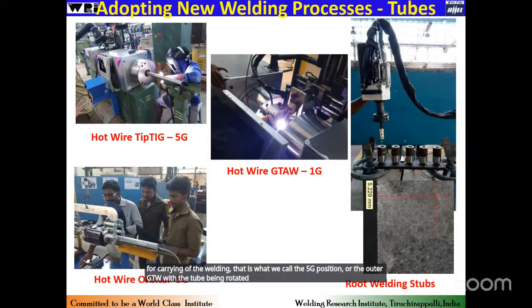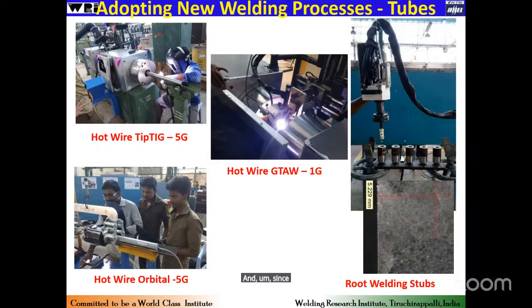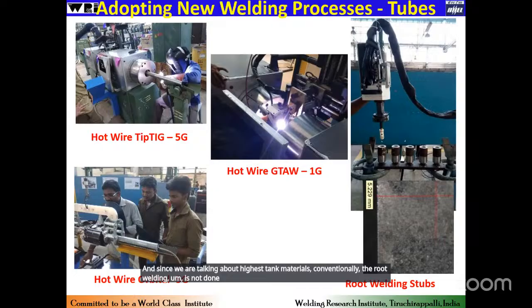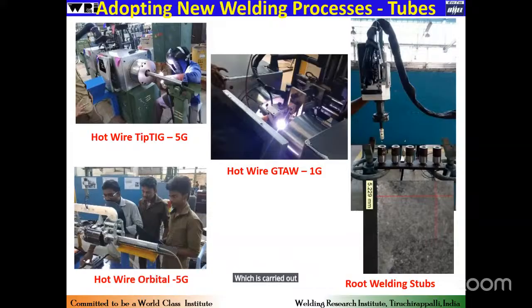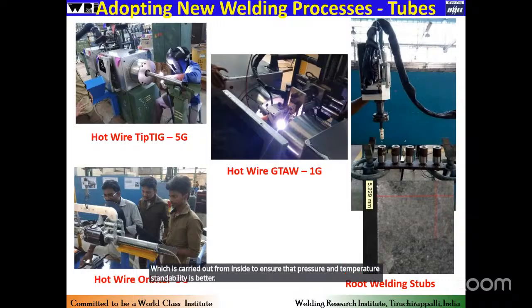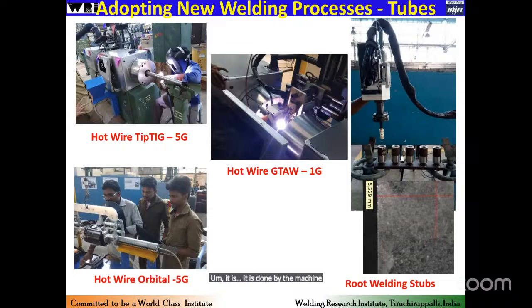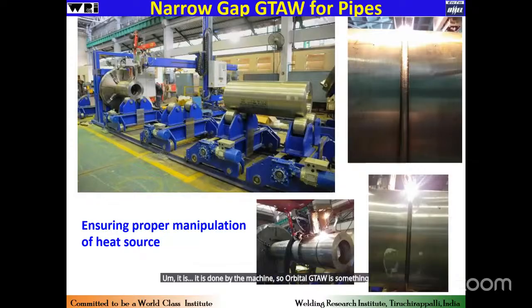And since we are talking about higher strength materials, conventionally the root welding is not done from inside, but this may need welding from inside. So this is the root welding of tubes, which is carried out from inside to ensure that its pressure and temperature withstandability is better. And of course, the orbital welding, where instead of a human maneuvering or manipulating the torch around the circumference, it is done by the machine. So orbital GTAW is something which we have optimized.